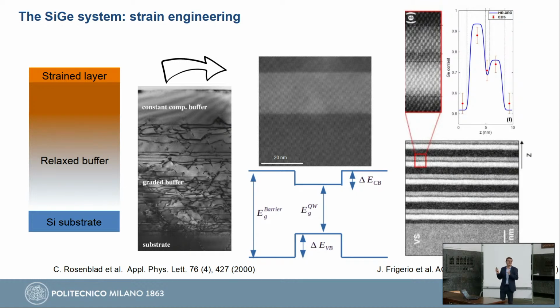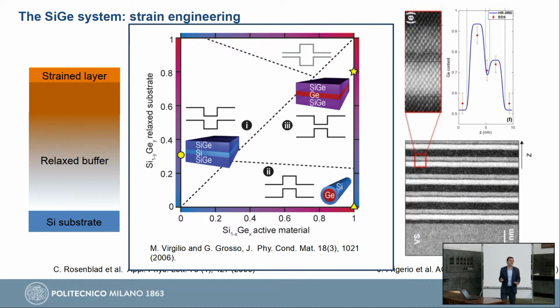So the main ingredient of whatever you want to do, single quantum well or coupled asymmetric quantum wells, is actually this one. You start from silicon, you grow a relaxed buffer, and then you use a strained layer on top of this buffer to play around with different quantum and physical properties. By doing this, you have a zoology of possibilities. Depending on the composition of the active material of the strained layer and the composition of the relaxed buffer, you have all kinds of band alignment. You can have situations where you confine electrons inside the well and holes outside, or the opposite, holes inside the well and electrons outside, or a situation where you have both electrons and holes together in the same layer.